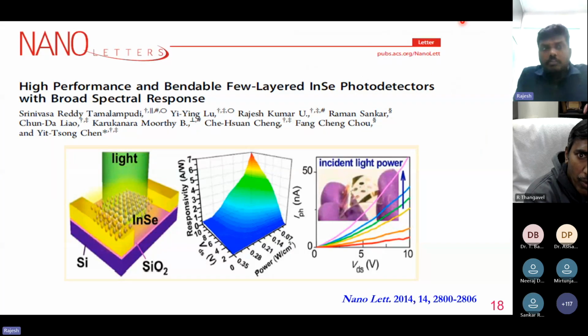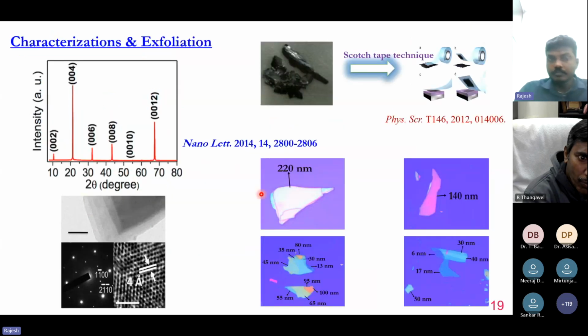So in this work, for the first time, we demonstrated that few-layered indium selenide can act as a high-performance photodetector. We grew indium selenide with the help of the Bridgman technique, obtaining a very large crystal, more than 2 centimeters in size, and exfoliated it with Scotch tape exfoliation, and demonstrated that few-layered indium selenide can act as a high-performance photodetector.